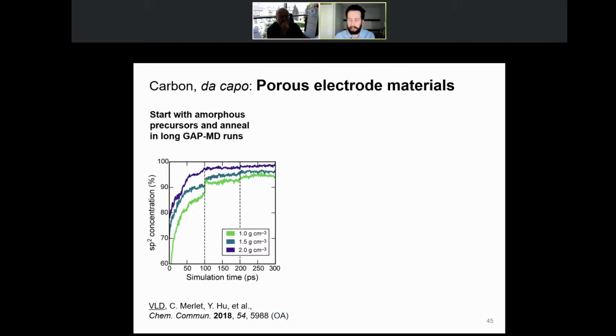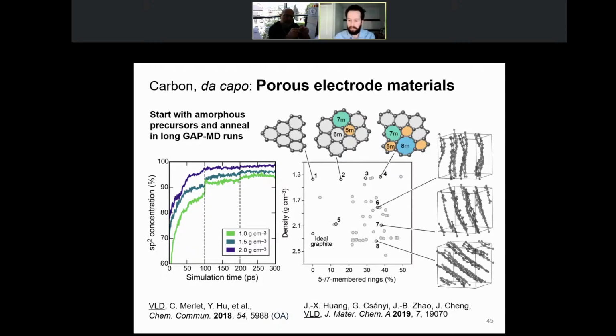So you get graphitized structures, and in fact, this is another project. This was done by Shanxing Wang from Xiamen University, who was visiting us, and he looked at all this parameter space in terms both of density and of local ordering, which I quantify here by the count of different odd rings in the structure. If I go across all this parameter space, I can say where the most representative structures are.